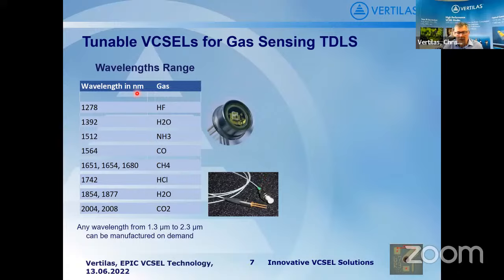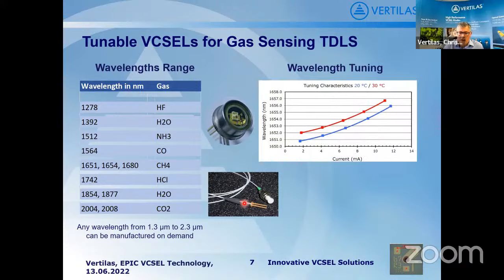To the left, you can see our standard product range starting at around 1.3 micron for hydrogen fluoride detection, and that's going all the way up to beyond 2 micron. And there are many TDLS gases in between: moisture measurements at 1392 or 1854, 1877, ammonia, carbon monoxide. Methane has already been mentioned in the first presentation, hydrogen chloride. So there are many standard products we manufacture, but on demand, we can manufacture actually any wavelength in this range. We have different types of packages, cooled and uncooled, open packages, or with a cap with integrated windows, or fiber pigtail packages.